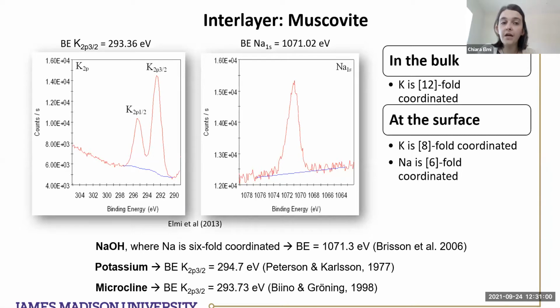Another story is the interlayer, where we can have potassium and sodium as a substitute. The coordination of this site should be 12 in the bulk, but at the surface it's 8 or 6. It means that there's a relaxation of the layer at the surface anytime that you split these layers. Anytime that you create this imbalance due to the peeling of a layer, what happens at the atomic level is a relaxation of the site, and later on a reconstruction of layers of charge that is related to the link with the molecules that are in the air, like water and CO2.